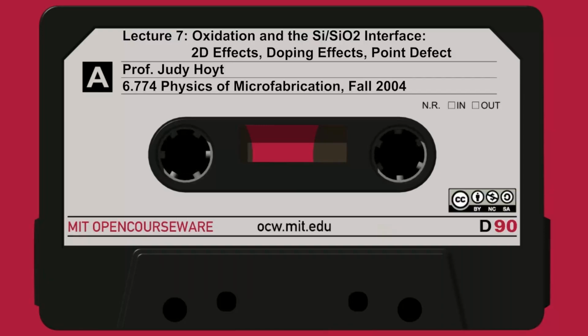So if I'm intrinsic, this goes to 0 and this term goes away. As this ratio increases and goes up above 1, this term starts to kick in. Interestingly, though, this model for the vacancy dependence is only going to depend on the electrically active concentration, because remember we said we move the Fermi level up. So if we add phosphorus to the wafer, it's only the amount of phosphorus that contributes electrons that's going to move the Fermi level around.